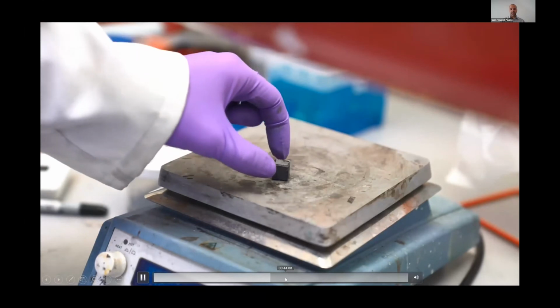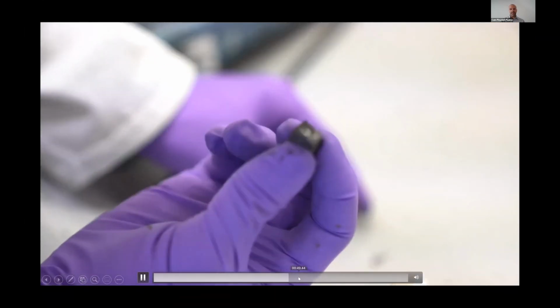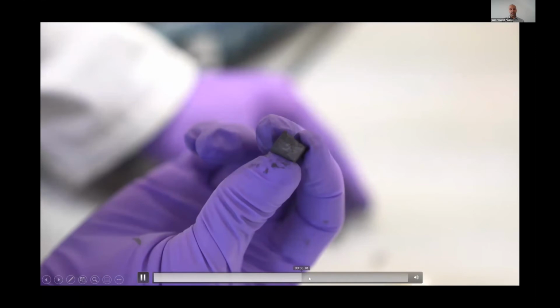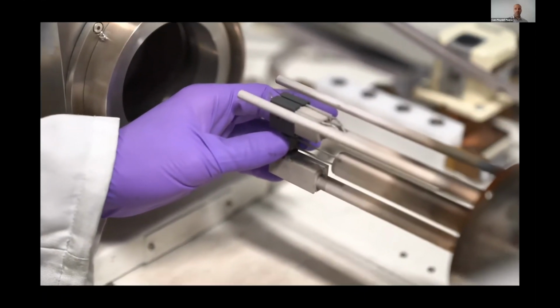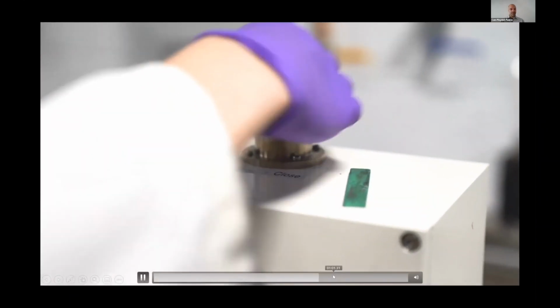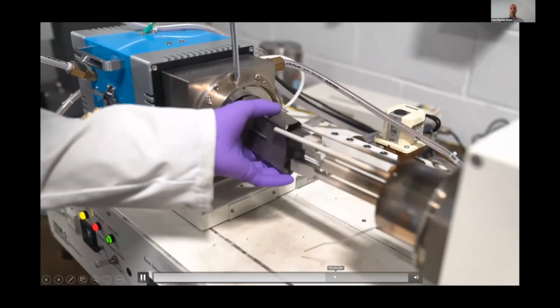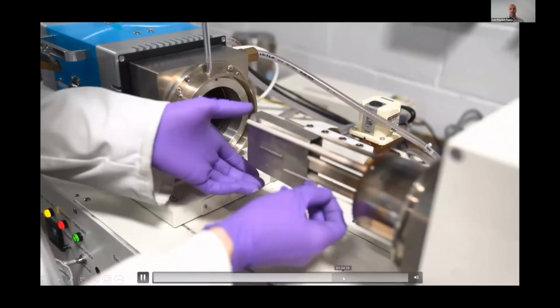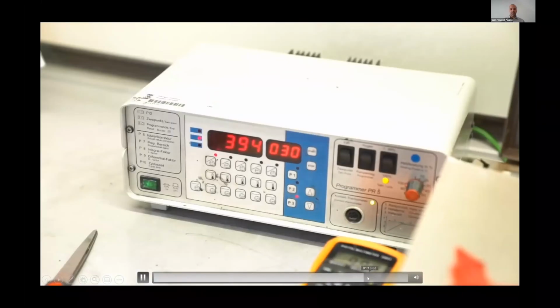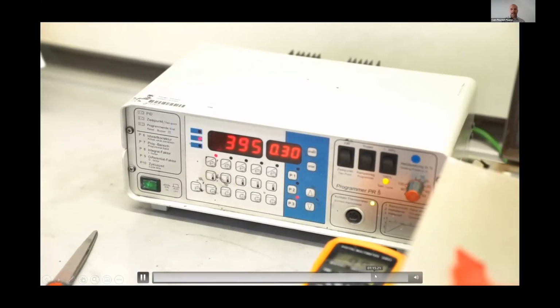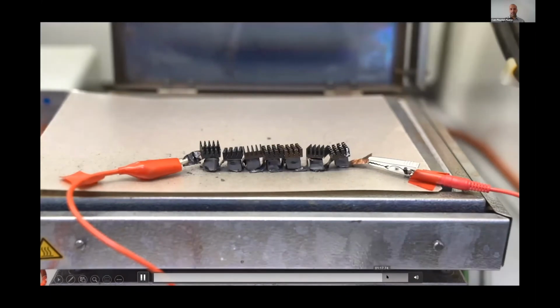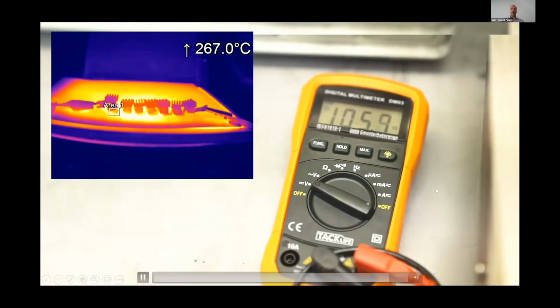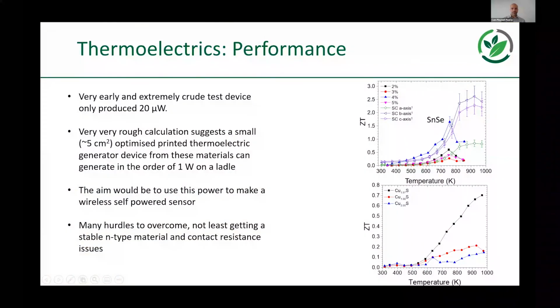Cure it for 2 hours, take it out of the mold, stick it in this machine here, which measures both the thermal conductivity and what's called the Seebeck coefficient, so how much that voltage in that leg changes as a function of the temperature difference, and then build devices, put them on a hot plate, and look at what sort of power output that we get from those materials as we heat them up. So how are we getting on? Well, the very early crude cases were producing about 20 microwatts, and that sounds tiny, but just let me finish.